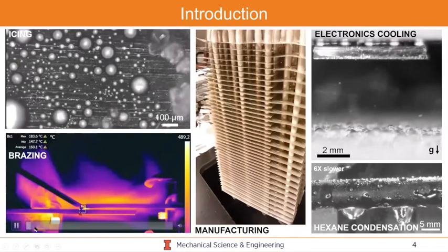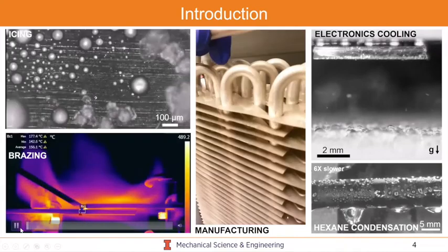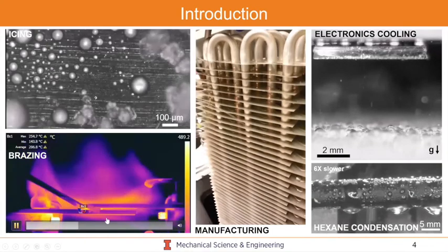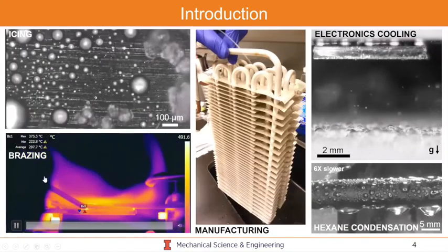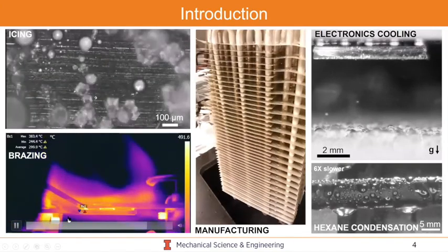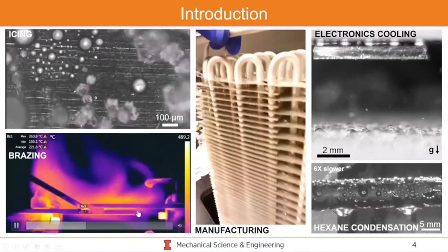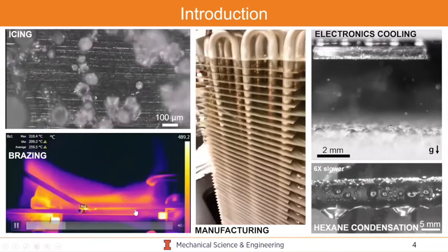And then on the bottom left here, I have an example where we don't just stick to low temperatures, we also do high temperature processes, where this is actually brazing of 2 copper plates. And by surface structuring the plates, you could actually enhance braze flow and make it go where you want it to go.